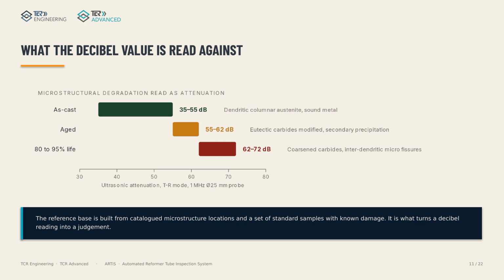A number on its own is not a judgment. TCR reads attenuation against a reformer tube reference base. 35 to 55 decibels corresponds to as-cast metal with dendritic columnar austenite. 55 to 62 indicates aged material where the eutectic carbide morphology has changed. 62 to 72 corresponds to 80 to 95% of life consumed, with coarsened carbides and interdendritic microfissures.